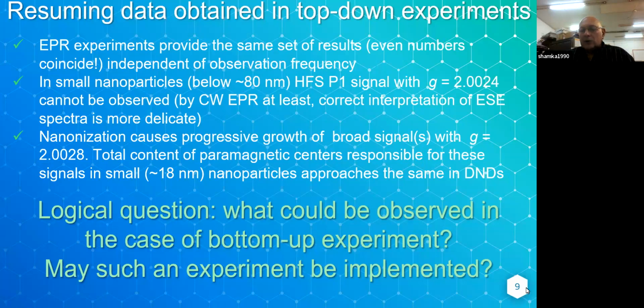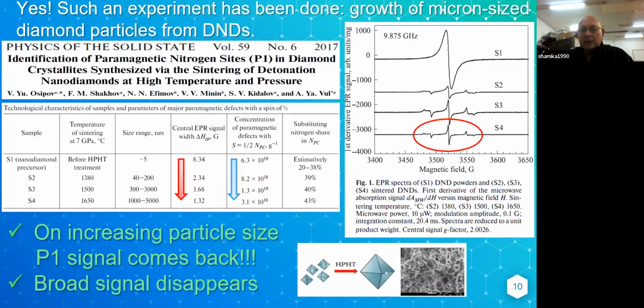Okay, we have a logical question. What could be observed in the case of a bottom-up experiment? All the previous experiments were top-down. We were taking larger crystallites and crushing them into smaller particles. Is it possible to make the reverse experiment? Start from small nanoparticles and then get larger particles. Indeed, this experiment was done. This experiment was done by this group from St. Petersburg.